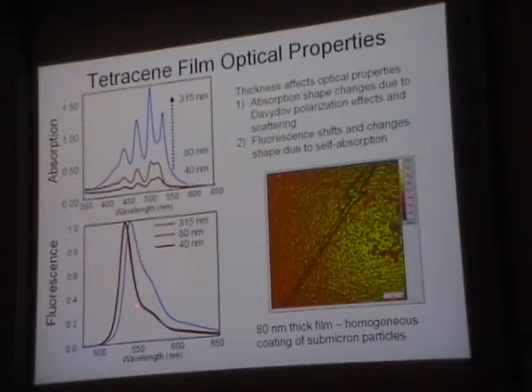You go from this nice thing that I was showing before, and if you make it too thick, all of a sudden it shifts red, and then the relative weights of the 0-0 and 0-1 peaks change. Again, you might think, oh, that means it's becoming less delocalized, but that's not true. It's just an optical effect, self-absorption. So there are a lot of optical artifacts that you can get in solid-state spectroscopy.